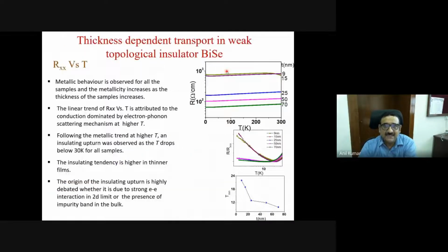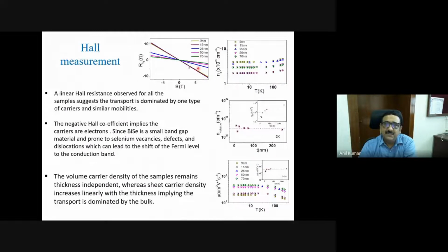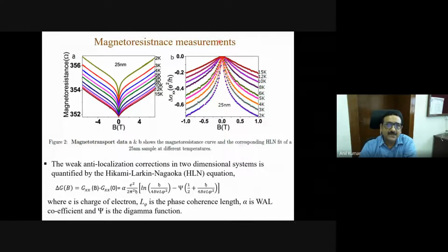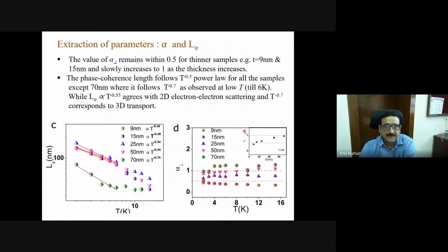So once we have this film, again, we do the Hall measurements, we find out how many conducting channels are there, we calculate the L_phi, we calculate the mobility of this film, and you see here the magnetoresistance for a 25 nanometer film. See, the magnetoresistance gives very nice weak anti-localization, and here also you see the conductance delta sigma is calculated. And then from there, we use the HLN equation to extract all the good parameters of this material. And again, the number of conducting channels for thicker films is 2 channels.